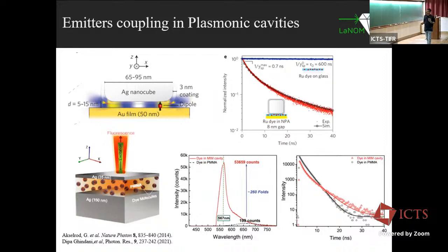One of the things you often see in the literature is that people talk about cavity coupling with enhanced emission intensity. You can see that by coupling a dye molecule in a cavity, there is around a 260 fold increase in emission intensity. But if you look at the decay rate, there is not much change. This is very important when you couple any emitter with cavities or a photonic structure. What you need is a change in the decay rate. Otherwise, you just have a filtering effect, and nothing more is going to happen.